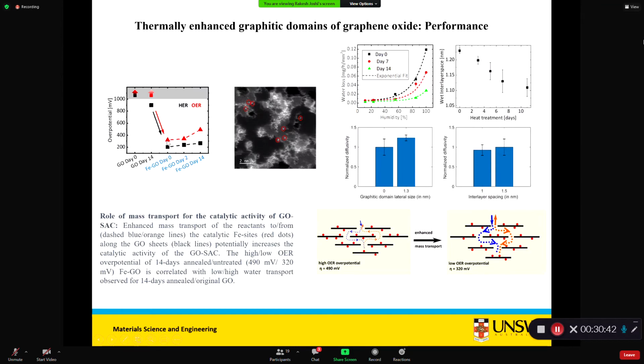And also, you know how we made this one? We just mixed graphene oxide and FeCl3. We didn't even heat it. So just by mixing and then stirring the solution, we can get an electrocatalyst, which is as good as the commercial benchmark. So this is another very nice application of graphene oxide. The same graphene oxide which we are making for membranes shows excellent performance when we use it for the catalyst.